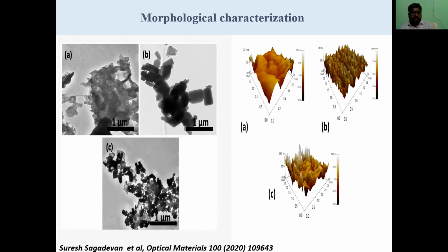And for the surface morphology characterization, you can really clearly understand that this is graphitic carbon nitride, which has a sheet-like morphology. Then this one is the hexagonal and cylindrical shape of the zinc oxide surface morphology, figure B. And C shows that both are there. You can see that this is the composite surface morphology. The sheet-like morphology is incorporated with the cylindrical and hexagonal shape of the zinc oxide nanoparticles. So once again we confirm the successful formation of this composite.